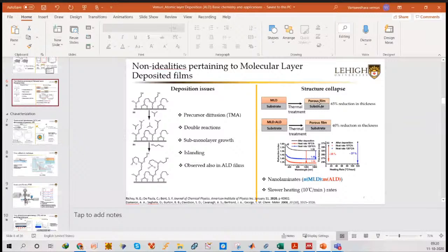To know if your sample is deposited uniformly on the substrate, you do many kinds of characterizations. One could be using ion scattering techniques. You can raster scan. Raster scanning means if you have a rectangular or square sample, you start at origin 0 and you go from 0 to 1 in X and Y directions, and you know the chemical composition at each spot. Sometimes you deposit thin films and see at spot 0 you have the chemical composition that you're expecting for aluminum, oxygen and carbon. That means that you have sample. And some places you have bare spots, meaning you're hitting the substrate directly. You get silicon and oxide. That's how you know that it is not monolayer, and that's how you know that it's not uniform.